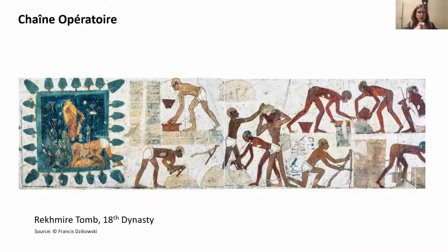Once the raw materials have been procured and some of them processed, as we have seen for the seagrasses, they were mixed together with water and blended for a couple of days, up to a week, depending on how long it will take for lactic acid actually to form and enhance the matrix cohesion of the mixture. We see traces of this final phase of kneading and pugging, especially when the mudbrick makers were preparing the mixing before the actual molding, in the microfabrics of the bricks.